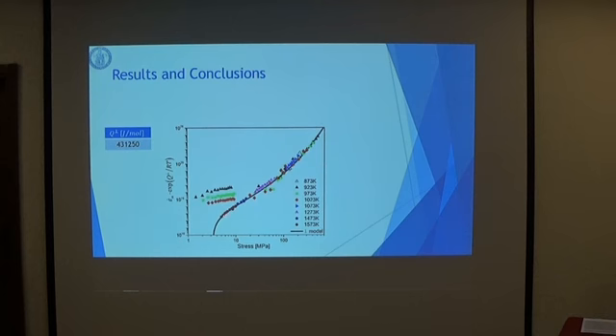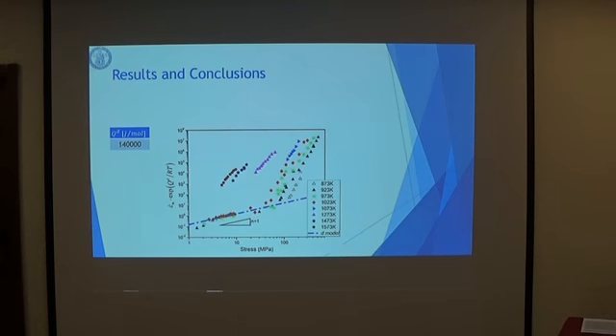As you can see, the data related to the dislocation deformation mechanism gather all together on this black line. We obtain this because with the normalization we are allowed to aggregate all the data which show the same deformation mechanisms. While the data which are scattered from this curve seem not to be related to this kind of deformation mechanism. Indeed, choosing an adequate activation energy for the diffusional contribution, we see that those data that were scattered on the other plot are all together on the line related to the diffusive model.